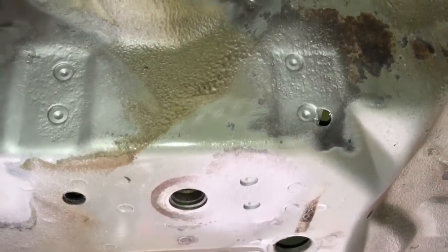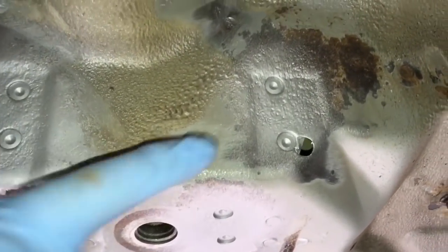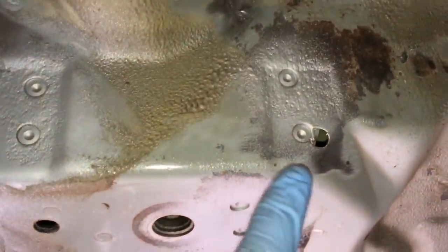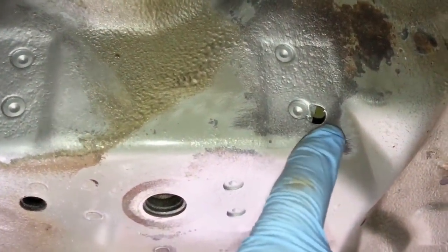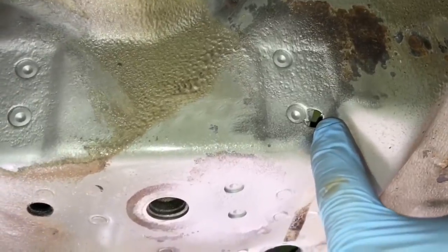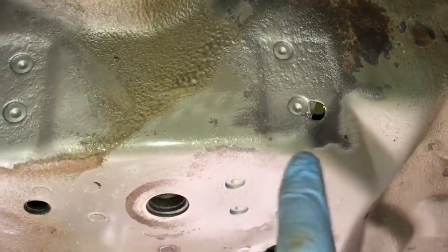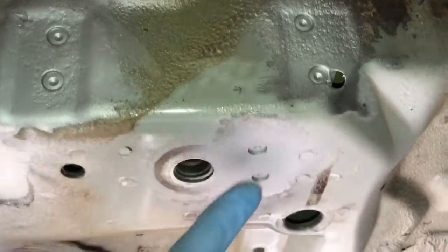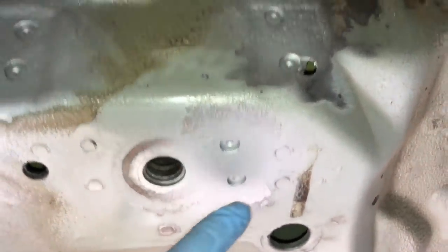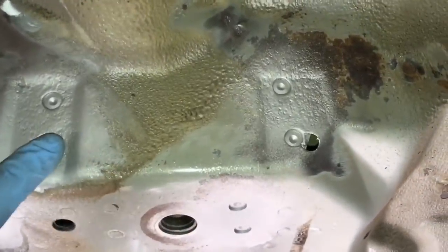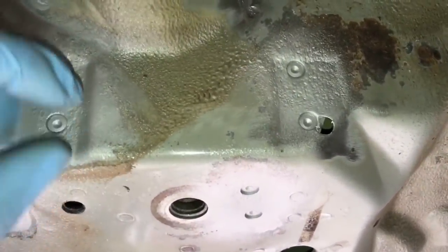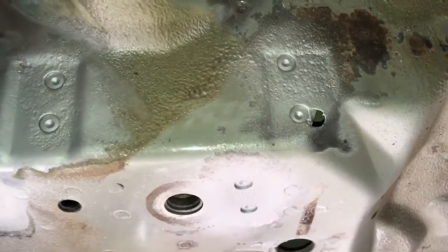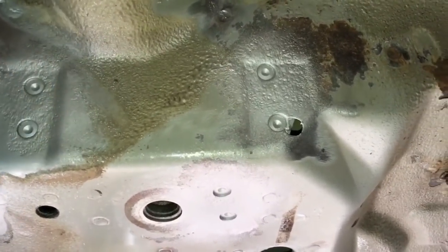We just drilled out a few more spot welds which were suspect. They've extensively flexed, which is what's brought in all this corrosion around them. There's two on this vertical plane, there's another two here, and this one had a crack going through it, so I've taken a section out and given an example of what the edge of the vertical wing looks like in the internal cavity. And there was two under here as well that were looking poor. To be honest, I don't think they had broken completely, but it's better that we replace them with a stronger penetrating plug weld rather than leave them there not knowing if they were cracked, for example.